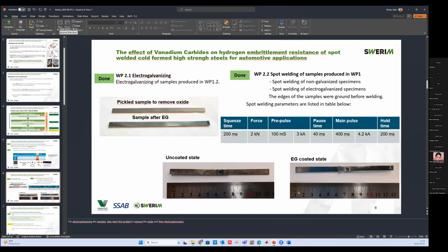For work package 2, just to illustrate, we did electrogalvanizing, and we used 2 different conditions of the materials: a pickled sample to remove the oxide coming from the Gleeble simulation, and an electrogalvanized one. On this slide you can also see the conditions that we used to spot weld the samples for the mechanical testing later on.